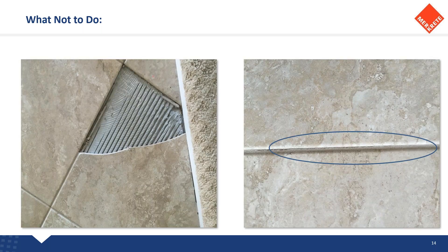Here's another instance — same scenario. We went out because of cracked grout joints. You can see the crack running down the edge of that tile, knuckling and chipping away from expansion, contraction, and movement. I started to pull up a piece of tile and once again I see those beautiful trowel marks — great straight lines — but we didn't achieve coverage or even transfer on this. They could have installed the tiles right back down on the floor. Some tiles have a lot of release mold dust from manufacturing on the back that needs to be wiped off prior to installation because it's a bond breaker. Again, we went out for cracked grout joints and found insufficient coverage behind the tiles causing them to be loose. It wasn't the grout's fault — it was the tile's fault.